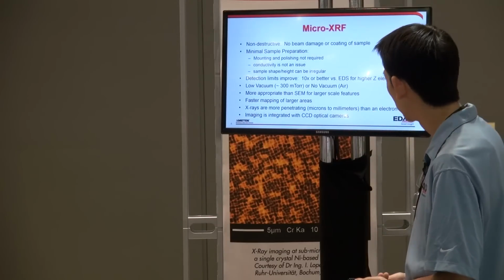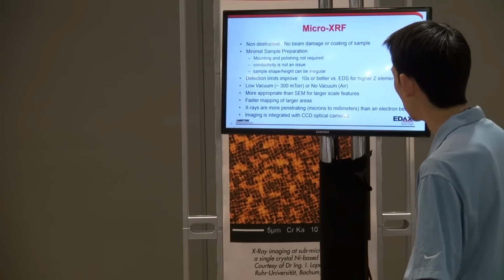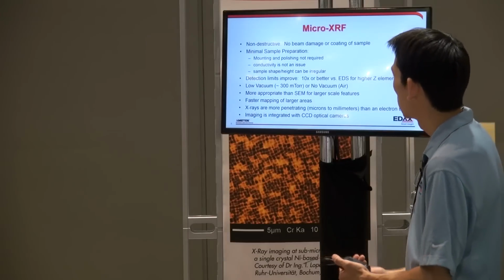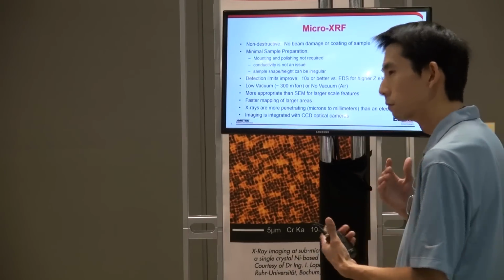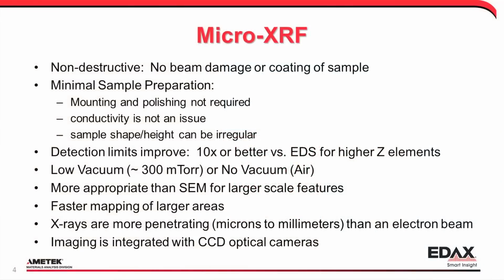It's more appropriate for larger scale features, as I mentioned, due to the larger spot size and the larger stage. You tend to map larger areas much faster, so areas that would take you days or weeks with EDS would generally take much faster with Micro-XRF, but you have a larger spot, so the resolution is a bit poorer with Micro-XRF. The X-rays, as I mentioned, are more penetrating, so sometimes they can even go millimeters into your sample, which gives you a more depth profile than just the surface chemistry. And also the imaging is done via optical cameras, which are integrated into the unit and not a second imaging unit, so that's a convenience factor.